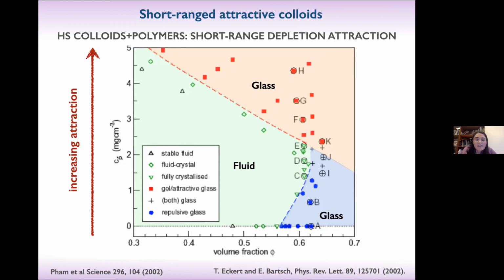If you are at zero polymer concentration, here along this line, you have just hard spheres and you go from fluid to glass. We neglect, as usual, crystallization because the systems are fully dispersed, and around 58% you have the occurrence of a glass transition, and the glass transition has this kind of shape as measured by experiment that goes actually towards larger packing fraction. And then up here, there is another glass line from fluid to glassy behavior.